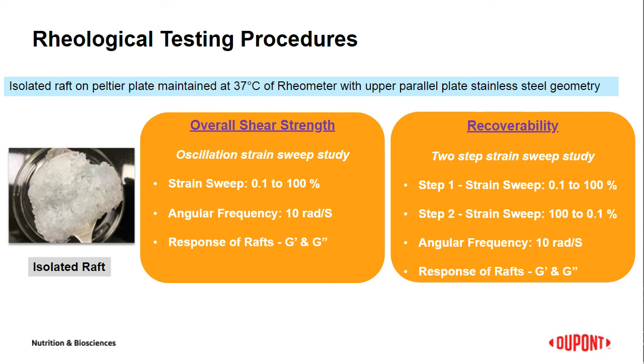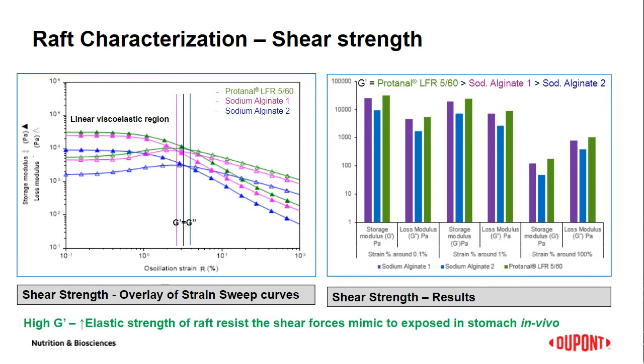For the second method, recoverability, similar to the earlier procedure, the isolated raft is placed on the Peltier plate and recovery of the raft is measured using two-step measurements. In step 1, the strain percentage is increased from 0.1% to 100%, and in step 2, the strain percentage is reduced from 100% to 0.1%. The response of the raft to the change in strain, that is low to higher and higher to lower, is measured in terms of storage and loss modulus, which are termed G prime and G double prime. So the results are represented in this chart.